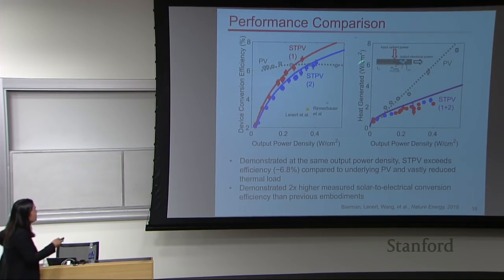So you see here, this is the heat generated as a function of the output power density. Here's a PV cell in the dotted gray, a fit to the data. And you can see that from our STPVs, there's a relatively significant reduction in the heat generated from the cell itself. It's about 2x or so. And so certainly you can think about this device as more efficient in terms of the conversion process itself, but also as reducing the thermal load. So it's effectively a thermal management strategy.